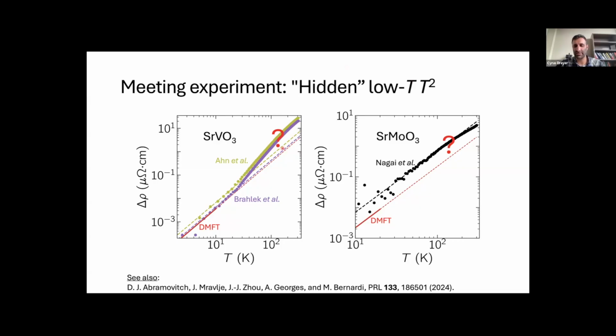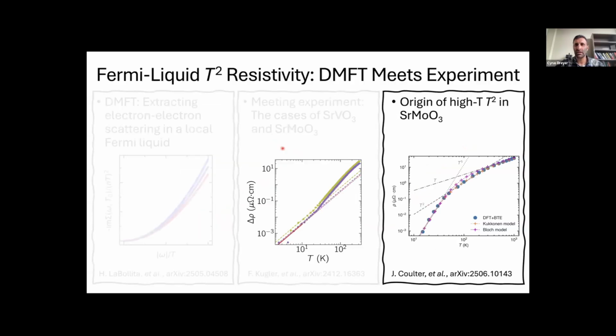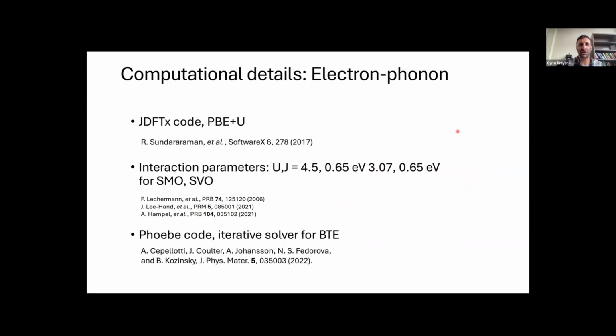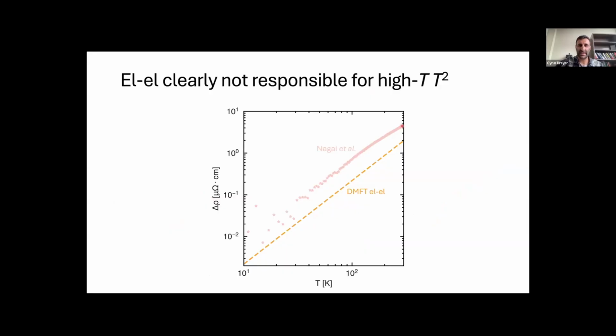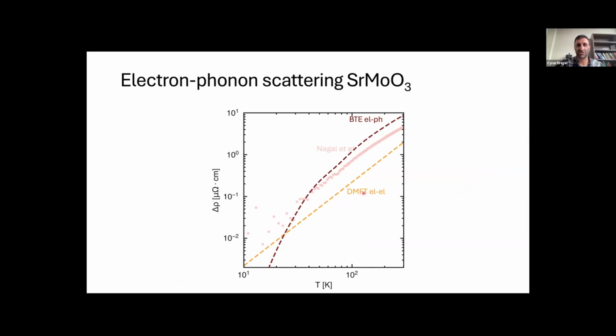But why do we have this high temperature T-squared regime? In the last couple minutes, I'll just quickly go over where this regime comes from, with the example of strontium molybdate. And of course, if it's not electron-electron, then the temperature scaling is probably electron-phonon. So with Jenny Coulter, we did electron-phonon calculations. Here are some of the computational parameters. I'll just skip right to the results. This again is that low residual resistivity strontium molybdate experiment. Here's our DMFT electron-electron calculation. And here is the electron-phonon calculation.